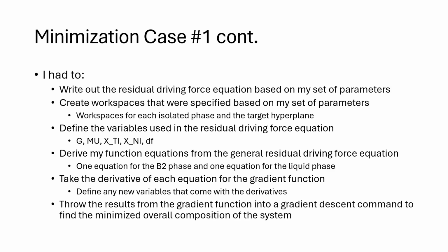So to find what I was looking for, I needed to write out the residual driving force equation based on my parameters, then create workspaces from it as well. I had to define the variables such as the Gibbs free energy, the chemical potential, the composition of titanium and nickel, and also define the residual driving force. I had to derive my function equations from the general residual driving force equation. I had to take the derivative of each equation for the gradient. Then I had to throw the results from that gradient into a gradient descent command to find the minimized overall